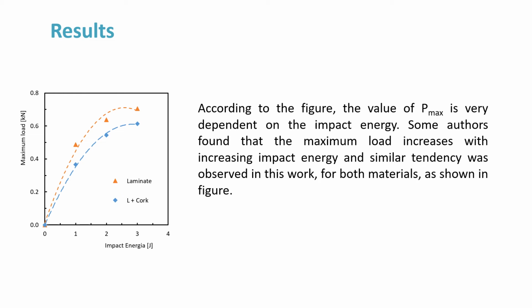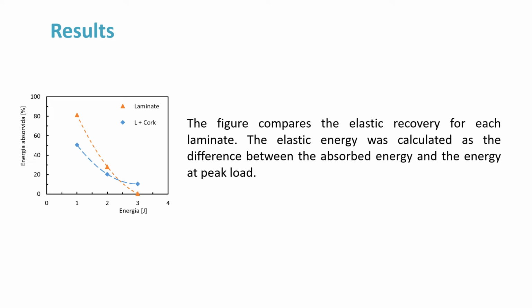According to the figure, the value of maximum load is very dependent on the impact energy. Some authors found that the maximum load increases with increasing impact energy, and a similar tendency was observed in this work for both materials, as shown in the figure. The figure compares the elastic recovery for each laminate. The elastic energy was calculated as the difference between the absorbed energy and the energy at peak load.